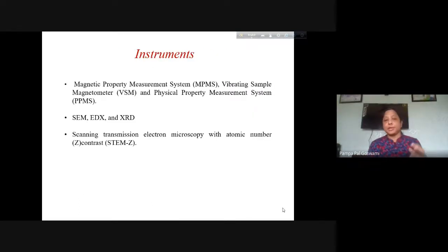So after preparation of these thin films, we have to characterize them by different instruments like MPMS, VSM, EDX, XRD, and STEM. So what can we do with these instruments? Magnetization measurements can be performed using an MPMS Quantum Design magnetometer operating in the RSO mode. The size distribution of NiFeCr particles and NiMn particles and the crystalline quality of both the matrix and the magnetic particles will be investigated by cross-sectional high-resolution scanning transmission electron microscope with atomic number contrast, because as we have different atoms like NiFeCr, we have to know which atom is where. So we can use the STEM instrument.